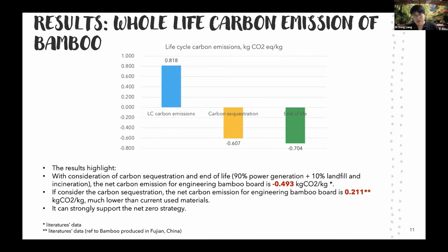And also, as I mentioned, bamboo is biomass and a plant, so it has the benefit of carbon sequestration. So if we think about the carbon absorbed in the process of the growth of the bamboo, we can further reduce the total life cycle carbon emissions. For example, the data from the paper shows that for bamboo grown in mainland China, like Fujian and Jiangsu province, the carbon sequestration benefit will be about minus 0.607 kilogram per kilogram of bamboo. And the number will also change due to the end of life.